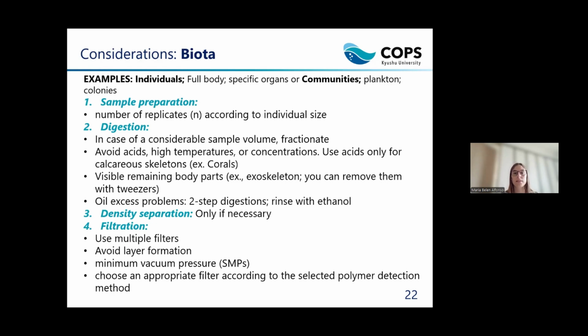And if you still see some visible remaining body parts, for example, some exoskeleton from the organisms, you can remove them with tweezers instead of increasing the temperature and increasing the concentration or the duration of the process to avoid particle damage. Always try to avoid particle damage, mostly for small microplastics because they're highly sensitive.